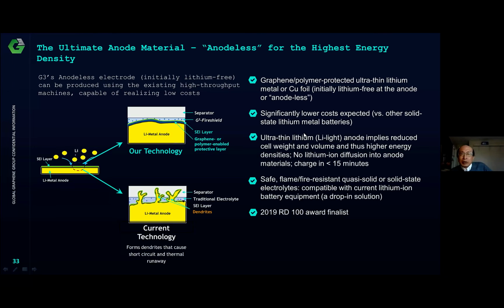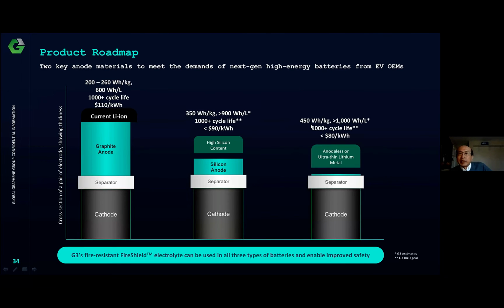And our goal here is to eventually achieve an energy density greater than 450 watt-hour per kilogram, and also greater than 1,000 watt-hour per liter, and then go beyond 1,000 cycles. And of course, along the way, also reduce the lithium-ion battery price down to below $80 per kilowatt-hour. Right now, it's about $110 per kilowatt-hour or so.